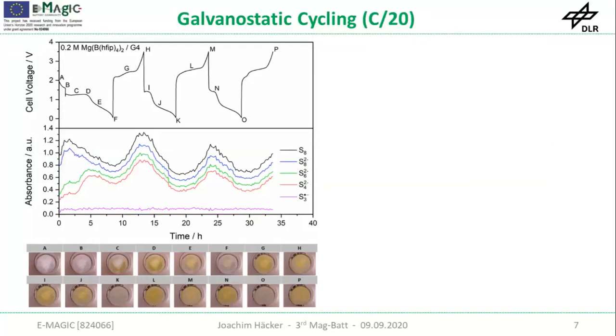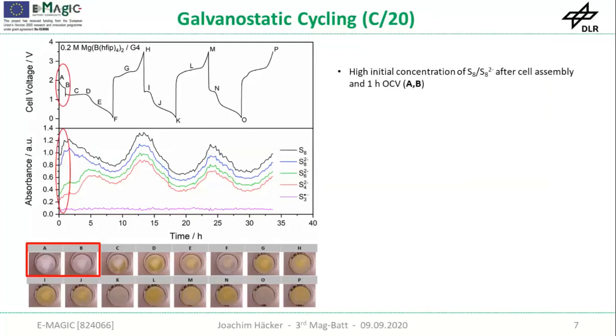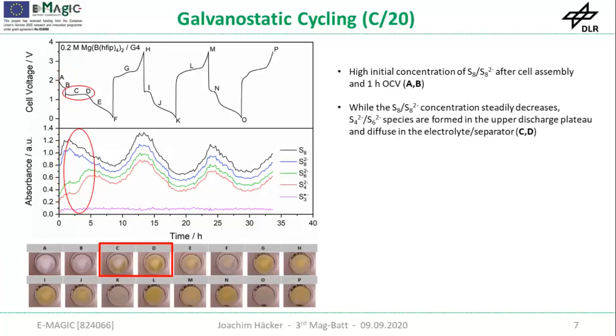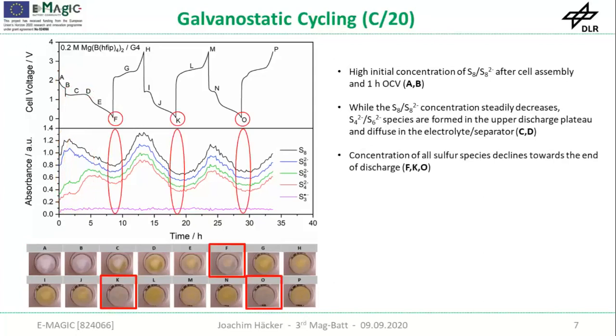To have a closer look at this behavior, I selected some stages here. You can see in the beginning there's already a high initial concentration of S8 and S8^2- after cell assembly. In contrast, the long or short chain polysulfides, MgS4 and MgS6, are not that dominant. They are formed during the first discharge plateau, and you can see that they cause this strong yellow coloration in the separator. Towards the end of the discharge, the concentration of all sulfur species declines, and the separator is decolored again. This is quite reversible, so it's observed in every cycle.